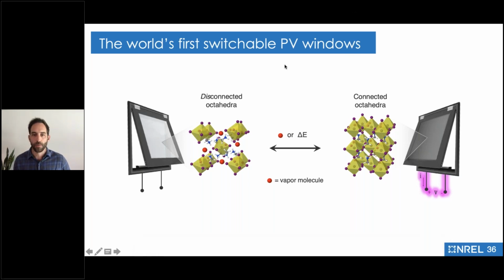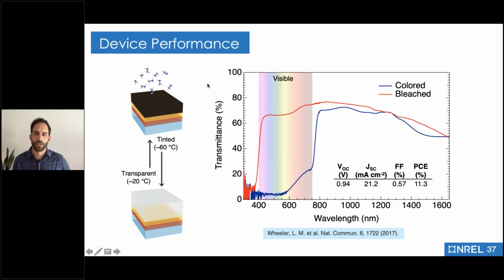So it was in 2017 that we actually pulled this off. We discovered that we could switch the color. Maybe 2016, we said, okay, let's make a device out of this. So we took this effect, intercalating and deintercalating molecules and making it go from this dark state to the light state. We put the layers around it that allowed for that phenomenon to happen. We can also extract charge, so make a full device. And now we've invented what I call the first thermochromic photovoltaic device that's ever been shown.